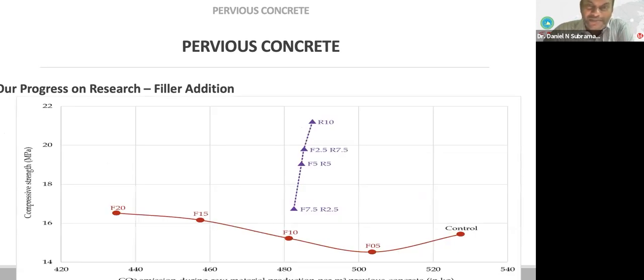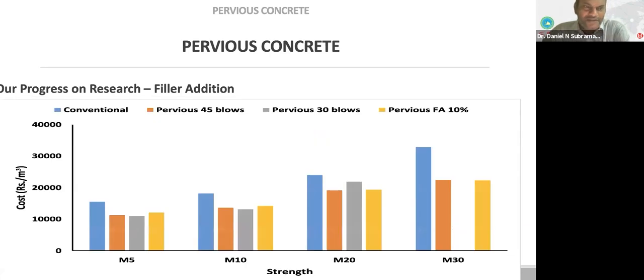So this is actually showing the compressive strength. F is indicating the fly ash, and R is indicating the rice husk ash. So this is showing you the compressive strength. Again, no compaction in this study as well. So you can see that rice husk ash addition is helping a lot with the enhancement of the compressive strength.